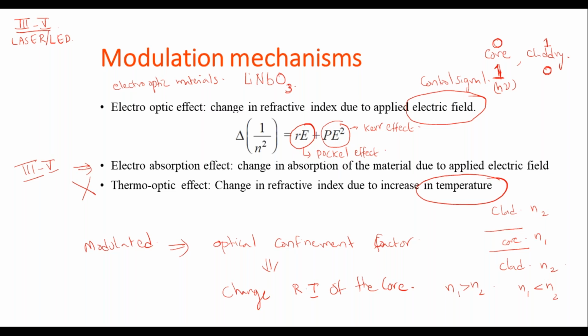So it is always advantageous to construct devices made out of the same material so that the device packaging becomes very easy. Unfortunately, whenever you are using this lithium niobate material, because it is not a III-V material, you cannot package it on a single substrate. And therefore, from the integration perspective, III-V based semiconductor materials have a significant advantage. So for the remainder of our lecture, I would mostly focus on III-V based modulators and devices.